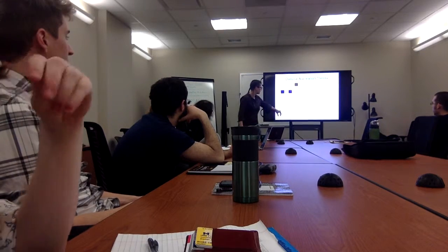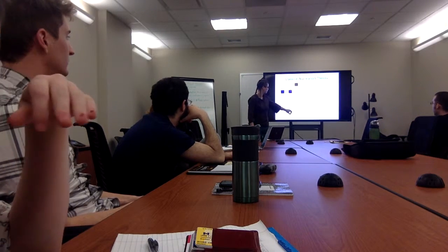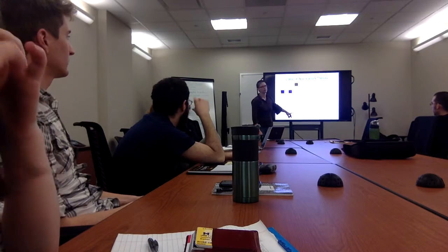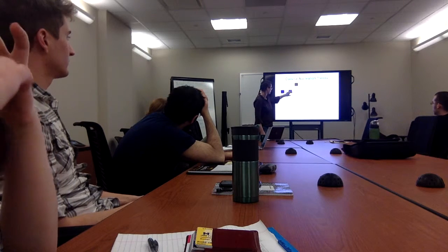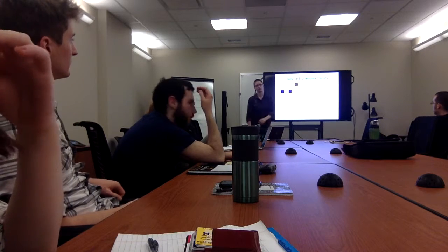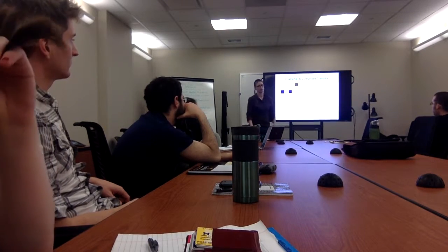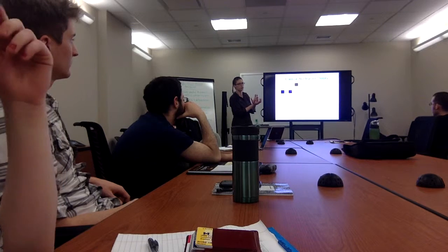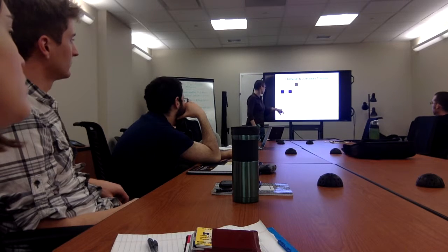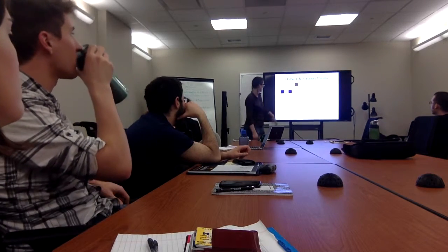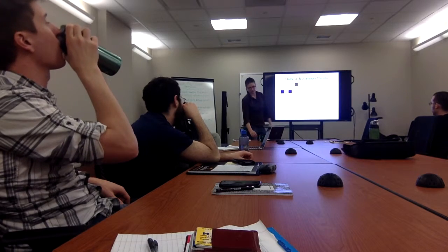The probability of this is the probability of hitting the nucleus. And it's a function of the self-diffusion constant, a measure of the average distance particles travel, and the average distance particles are from the nucleus, sorry, and the amount of area they have to attach to. So the number of particles in the nucleus to the two-thirds is roughly the number of surface particles. So it's an approximation of how many sites there are for a particle that's joining to join on. So this part of the kinetic term is the probability of something attaching, which is the diffusion length, diffusion rate, and the number of sites to diffuse to.